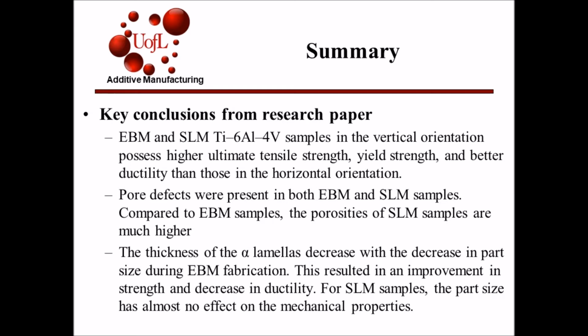For the first one, it was EBM and SLM titanium alloy samples in the vertical orientation possessed higher ultimate tensile strength, yield strength, and better ductility than those in the horizontal orientation. The second conclusion was that pore defects were present in both EBM and SLM samples, but compared to EBM samples, the porosity of SLM samples was much higher.